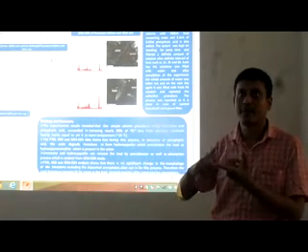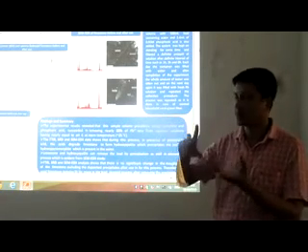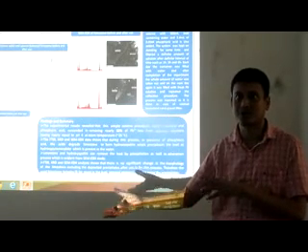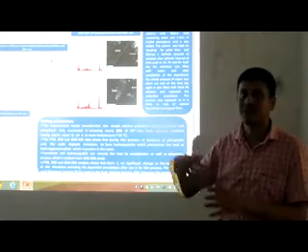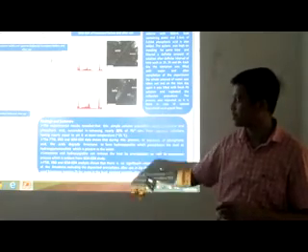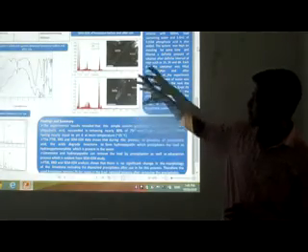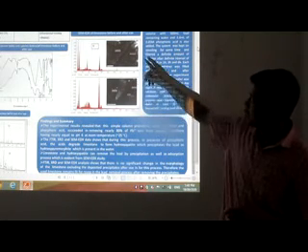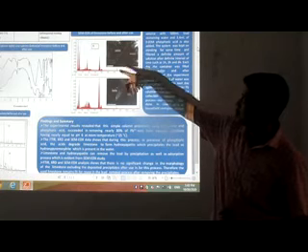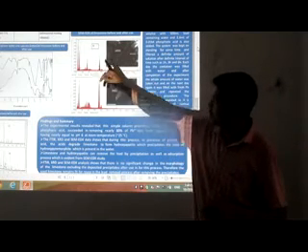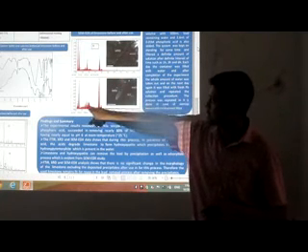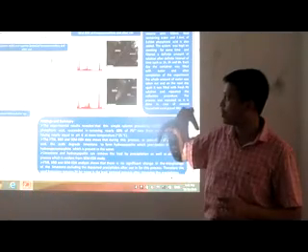That means the limestone is reacting with the phosphoric acid to produce the hydroxyapatite, which has again precipitated the hydroxypyromorphite. After that, we have taken SEM-EDX and done the elemental analysis, where we have found that in the first one, which is before use, there is no peak for lead, but in the second one there is a broad peak of lead. That means the surface of the limestone is having some amount of lead.